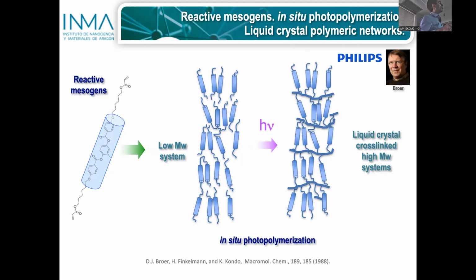But if we use liquid crystal molecules that are provided with acrylate groups at the end, with reactive groups at the end, we can orient them in the liquid crystal in the low molecular weight state, as we saw in the previous slides. By including a photoinitiator in this system and exposing it to UV light, we excite the photoinitiator, and then we grow polymeric chains. We link these acrylate groups, forming a polyacrylate chain, and fixing in this way the orientation that we got in the low molecular weight. So we can play with the low molecular weight system and generate with this a cross-linked system.